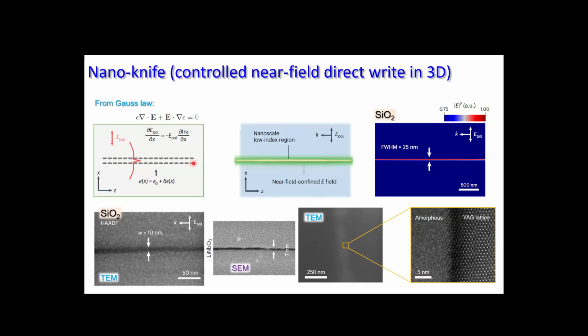And this is slightly different from the previous case when we have really ablated material and low refractive index sitting in a nano hole. Here we have a situation where on the optical axis at the center of the peak we have ionization of material, so it begins to be more absorbing. So refractive index is decreasing because we have more electrons on the optical axis. And then just from Gaussian law, we can derive that localization, this is not a waveguiding mode, this is a near field mode, it's not propagating light, but it will be happily sitting in the place where refractive index is slightly smaller for this orientation of polarization.